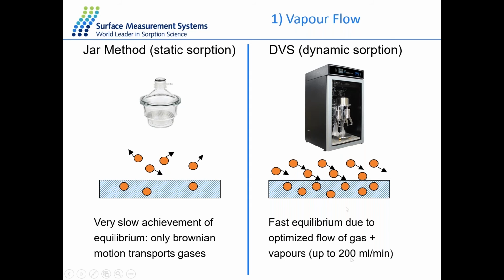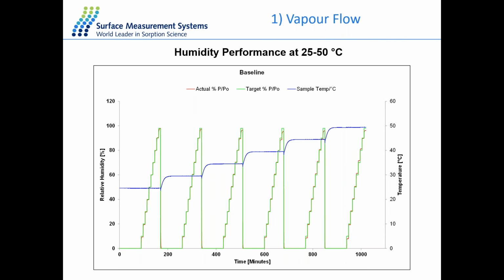For example, in the DVS experiment, we can reach a full sorption-desorption experiment within 3 days, compared to several weeks or even a month for the single point in the jar method. And the actual humidity or partial pressure is always measured by the sensor inside the system, and this will make sure the performance of the system with a very good and accurate measurement.